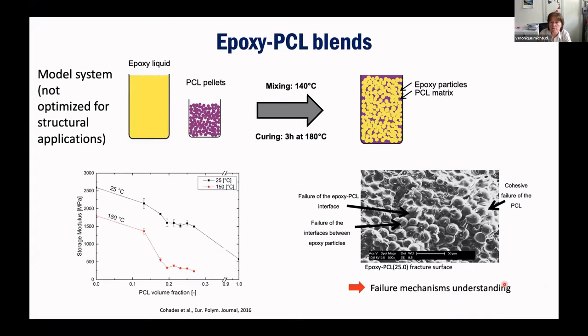So we worked on these PCL blends and we decided to use them as a matrix for a composite. First step was, of course, to use it as a matrix and see what it does. So we mix the PCL epoxy at 140 degrees. Then we cure, we had a DDS hardener at the time. We cure 3 hours at 180, and we have indeed the phase separated structure that we were expecting.